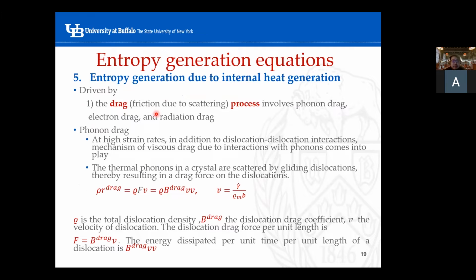In this case, we have to start considering internal frictions because in the ultrasonic vibration fatigue, there's a mechanism called the drag process that involves phonon drag, electron drag, and radiation drag. And we figure out that at this frequency, the phonon drag is actually the most dominant dragging mechanism among these 3.